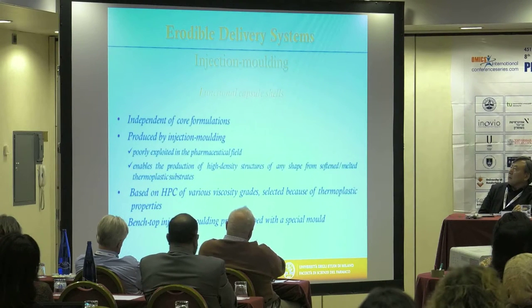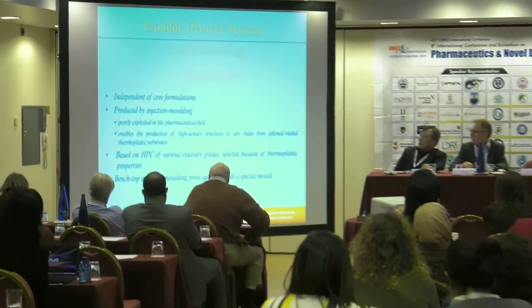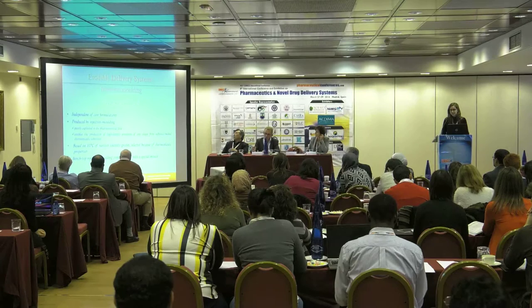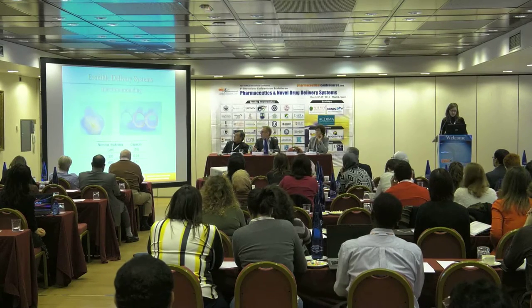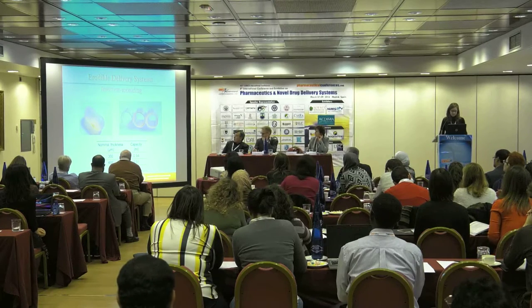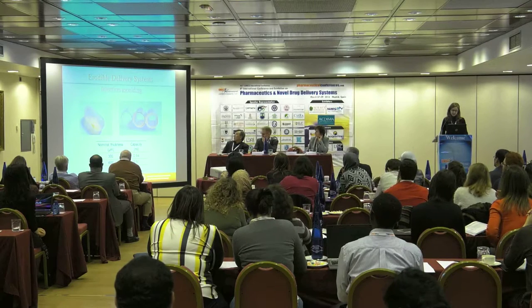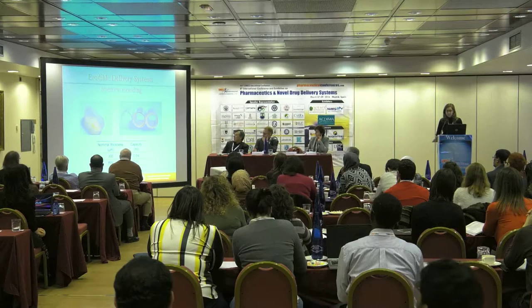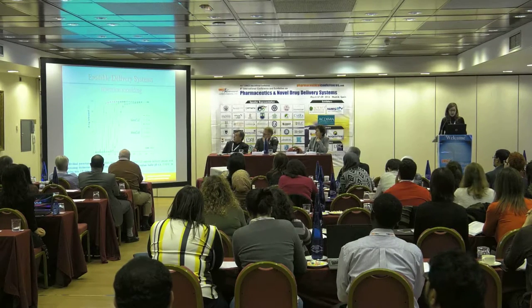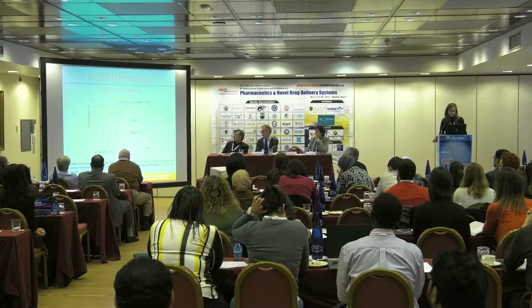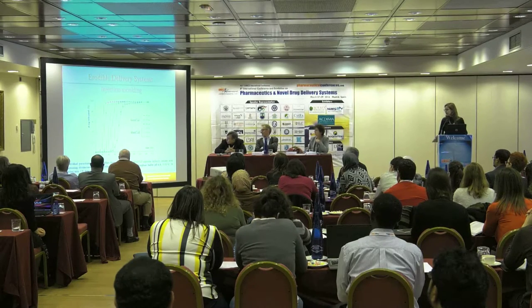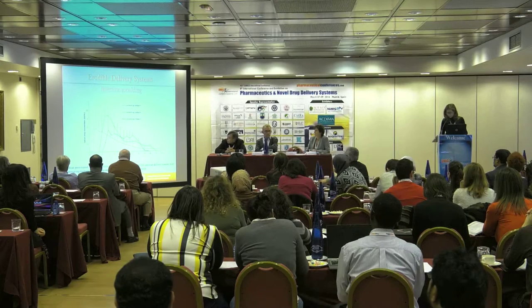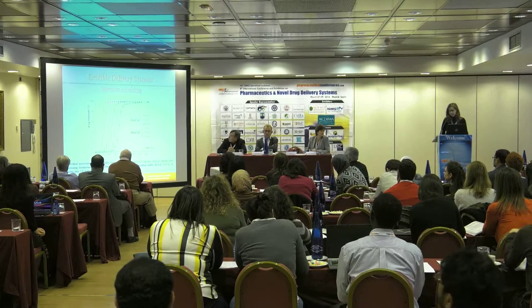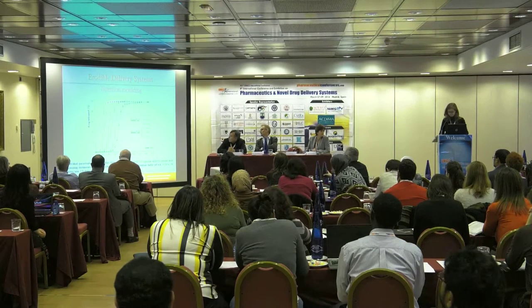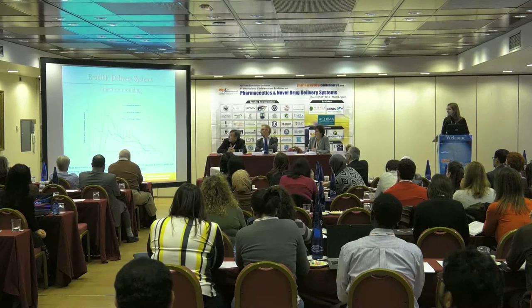Hydroxypropyl cellulose was chosen as the shell-forming agent because of its relevant thermoplasticity, and a benchtop injection molding press provided with a special mold that was designed on purpose was employed. Caps and bodies of capsule shells having differing nominal thickness values were obtained within automated cycles of a few seconds. And in vitro studies pointed out a rapid release of the model drug contained in the assembled capsule shells after lag phases that depended on the polymer viscosity and on the thickness of the shell. This behavior was well reflected in vivo.